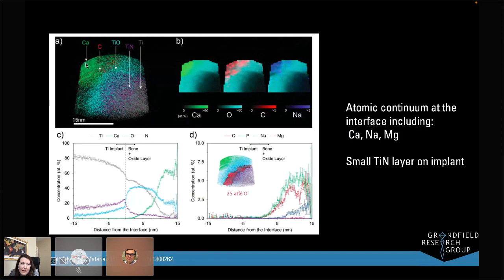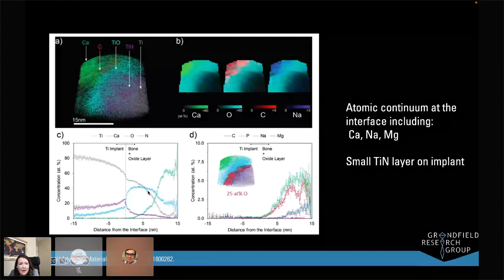We can perform a line scan across this 3D volume and map out the different chemical compositions. We can see that there's a strong intermixing of titanium from our titanium dioxide and our calcium phase across quite a broad interface.